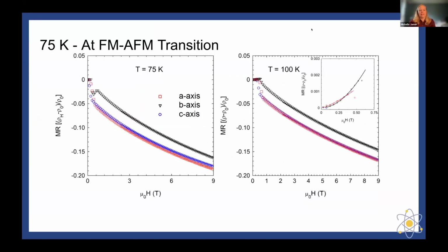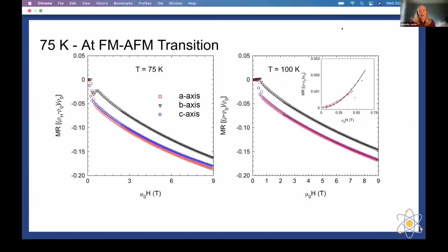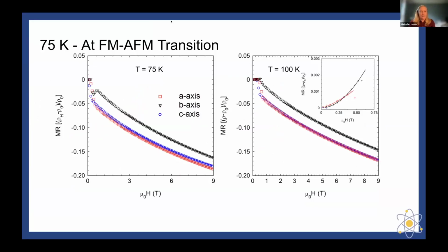If we were to take a look at 75 Kelvin, that is the temperature that's closest to the ferromagnetic-antiferromagnetic transition, we just start to see that our positive magnetoresistance along the B axis dies out. So it's still there when you are in the antiferromagnetic state, it's just much smaller. If you take a look at the inset of the 100 Kelvin data, it still exists along the B axis, and then it actually starts to occur also along the A axis because now they're in similar magnetic states. So while it's smaller, it still persists.